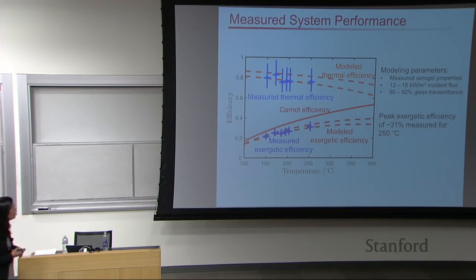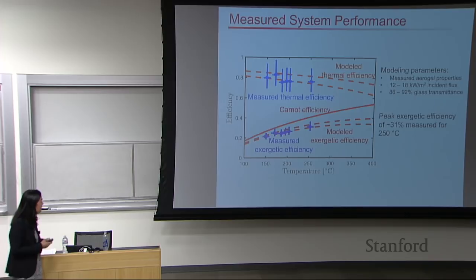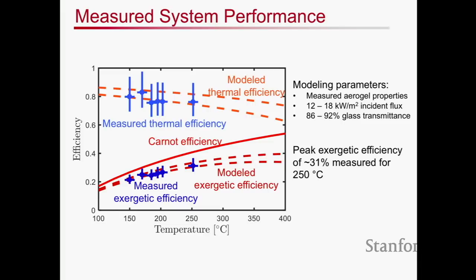And these are results that suggest significant promise in this. This is looking at the efficiency as a function of the temperature. The blue dots are the data that we've obtained from these measurements. You can see here from our modeling that we have very good agreement in terms of what is possible in terms of the thermal efficiency and also the exergetic efficiency that's modeled and also measured.